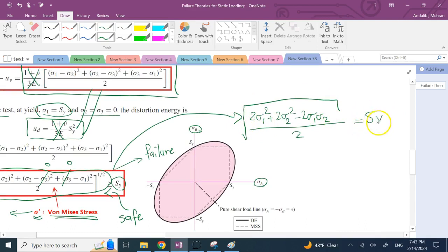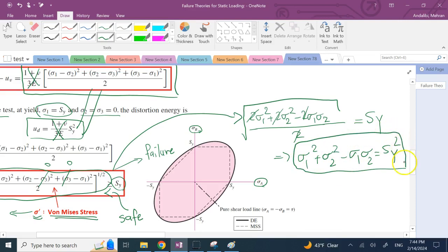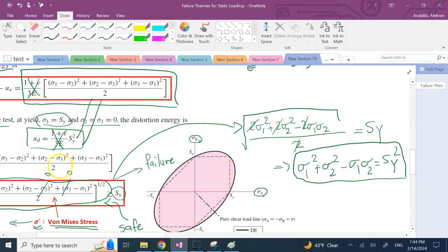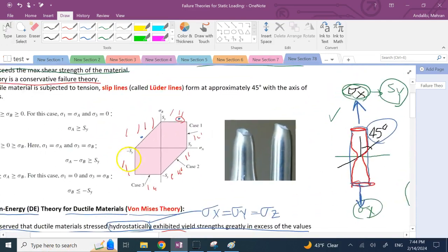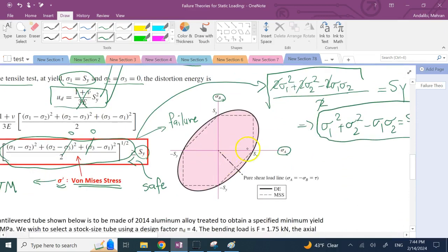If we look at the equal sign, we get the boundaries of the failure region. Clearly, we can get rid of all of these 2's. And if you square both sides, that becomes sigma 1 squared plus sigma 2 squared minus sigma 1 sigma 2 equal to Sy squared. And you know this is the equation of an ellipse that is rotated by 45 degrees. And that is exactly what you can see here, a rotated ellipse. An interesting thing about this ellipse is that if you draw the Tresca hexagon, it falls right inside this ellipse, with its corners, which are Sy and negative Sy, being right on the boundary of the ellipse.